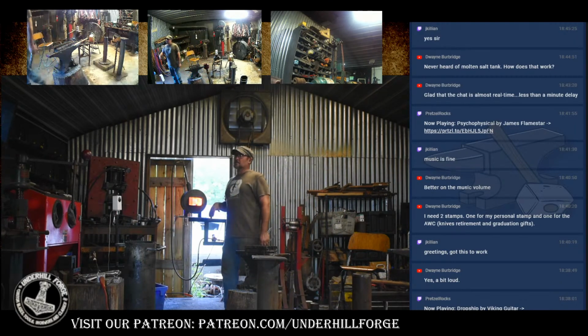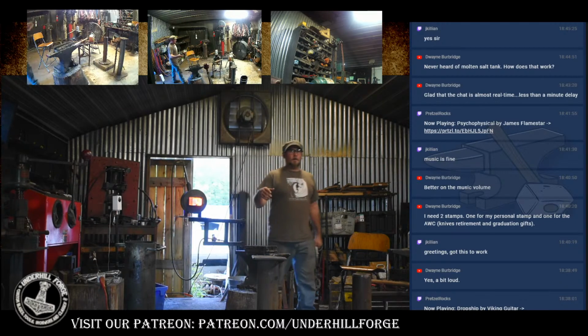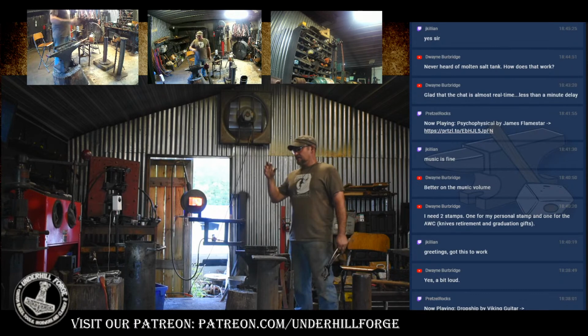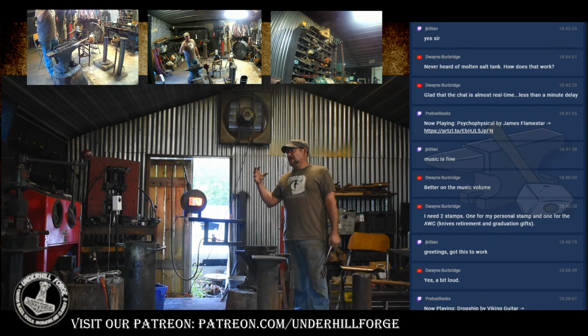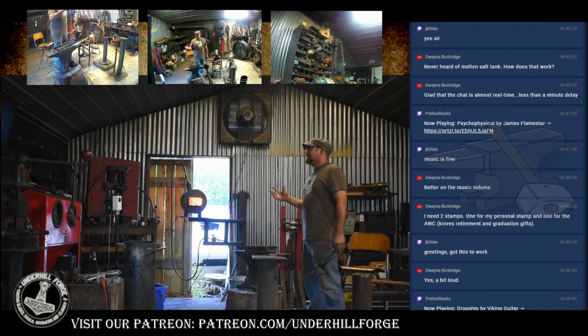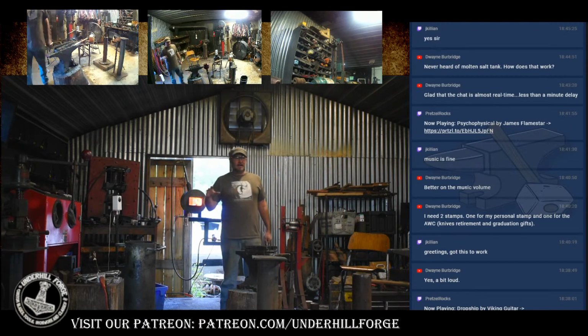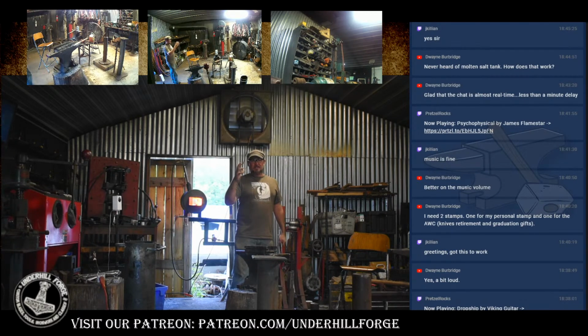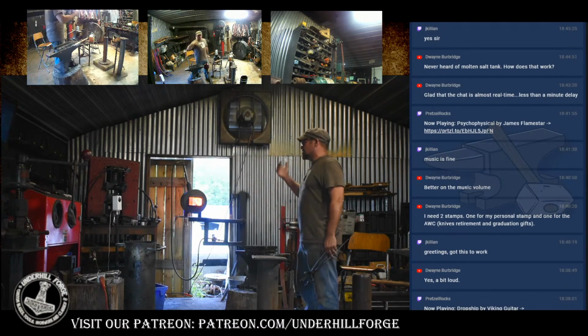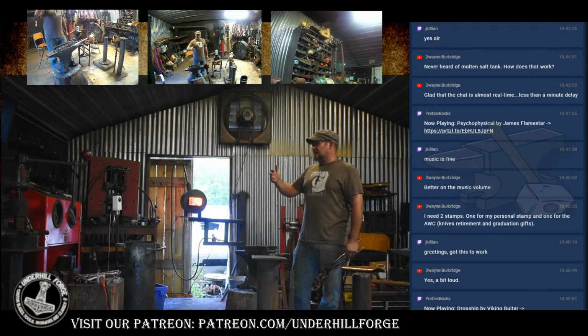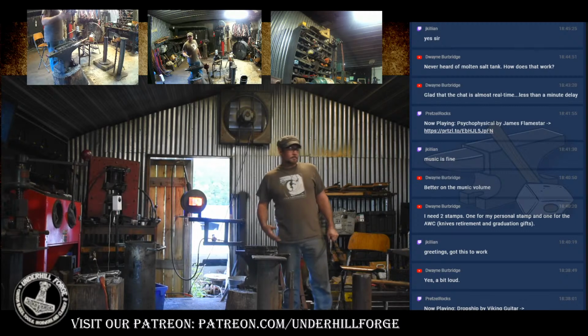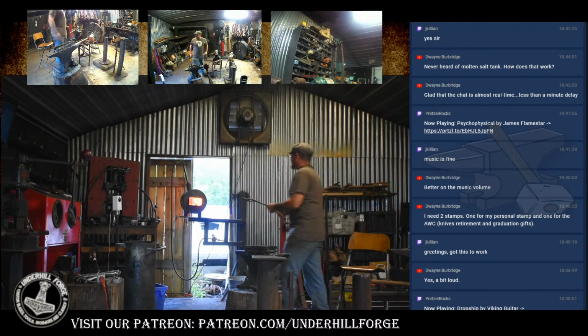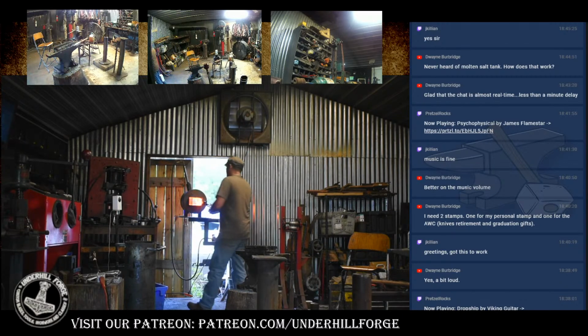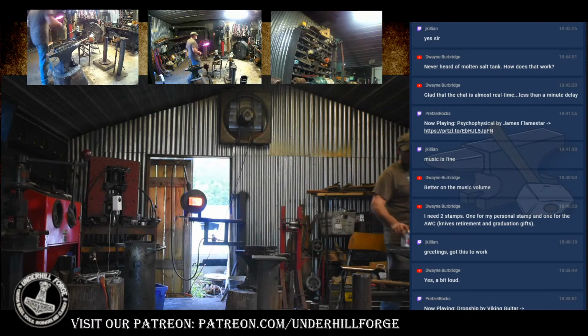It only works with certain steels, but I can do it with 1095, where I can come out of the electric oven at 1475, and depending on what kind of modulus of elasticity I'm looking for out of the 1095, I can quench it at, say, 550 to 650 degrees, and instead of having to go through hours of tempering cycle, I can get it done in about half an hour. But unfortunately, it does not work with all steels.